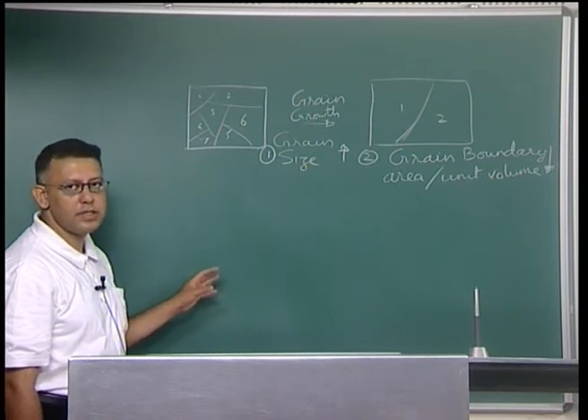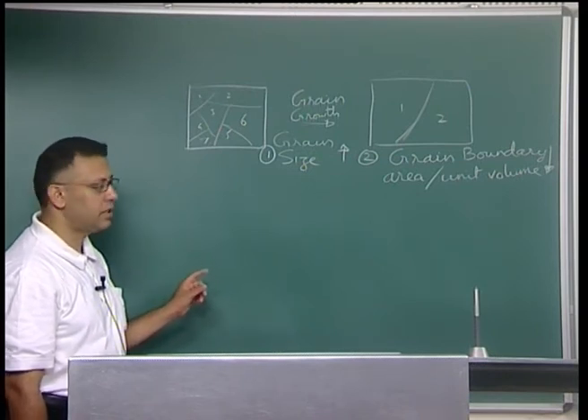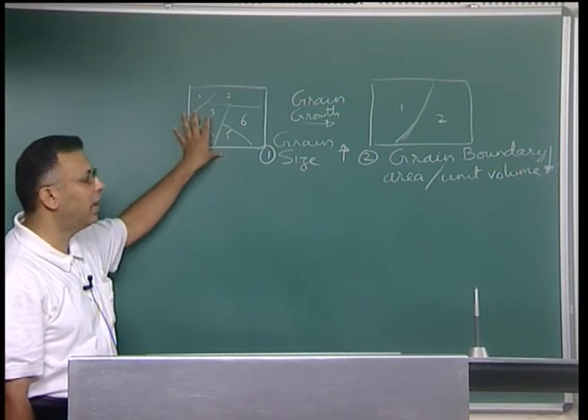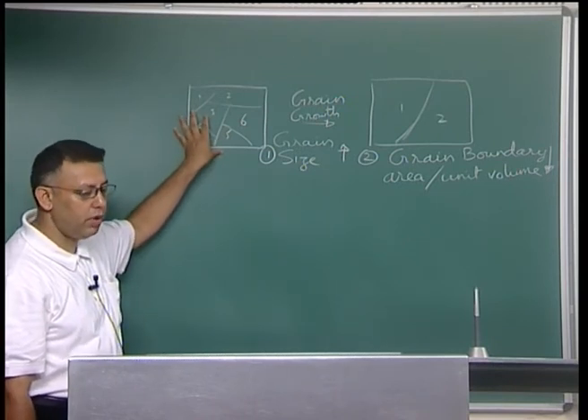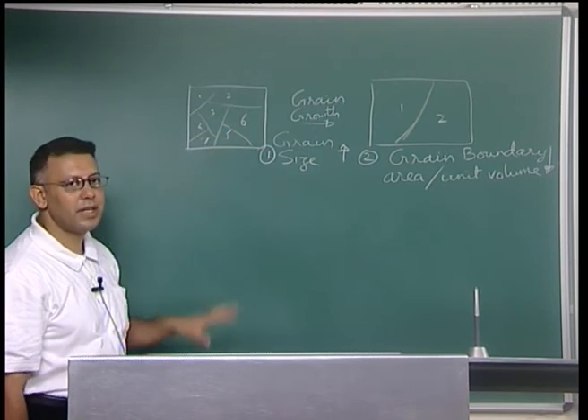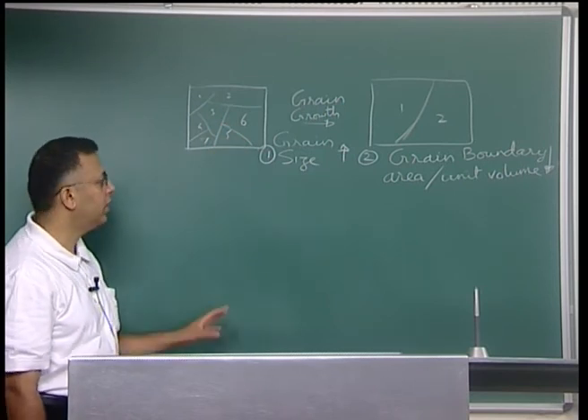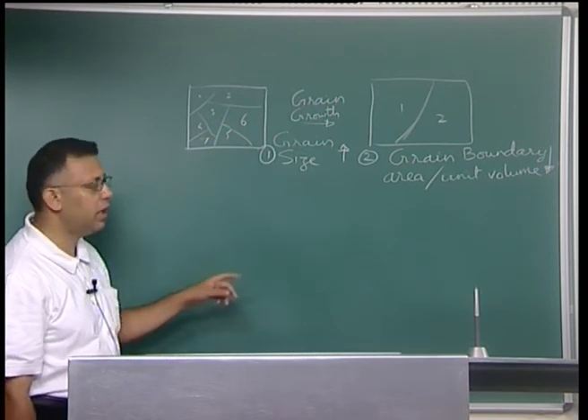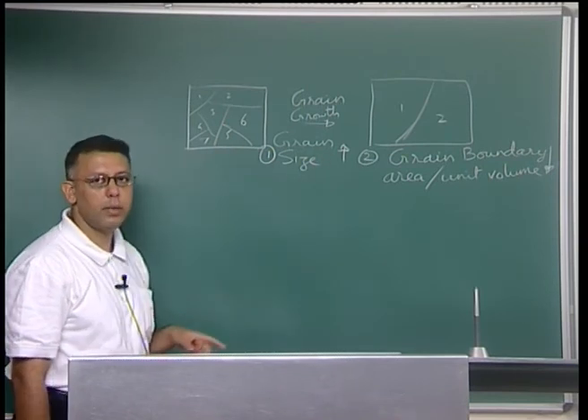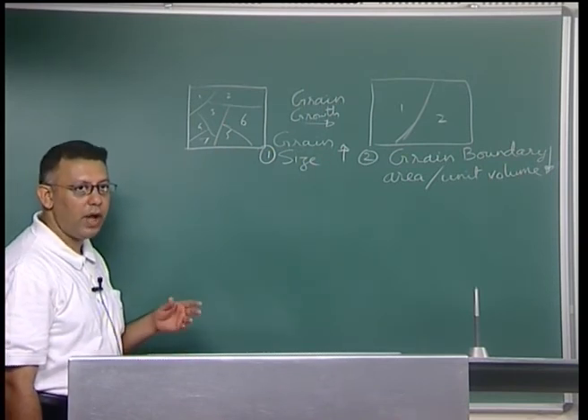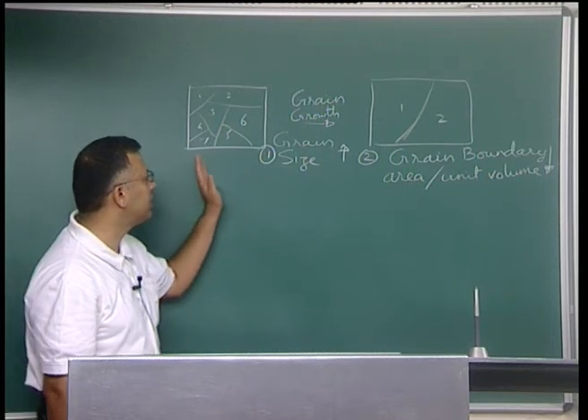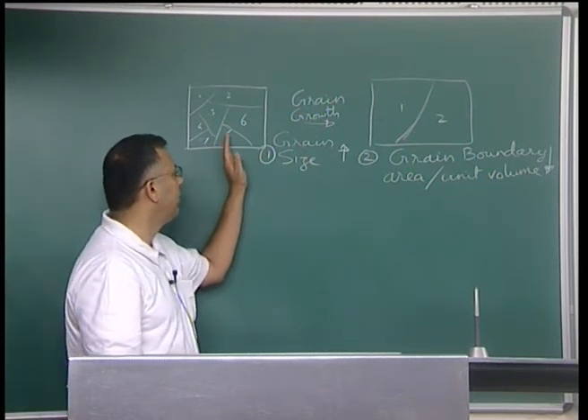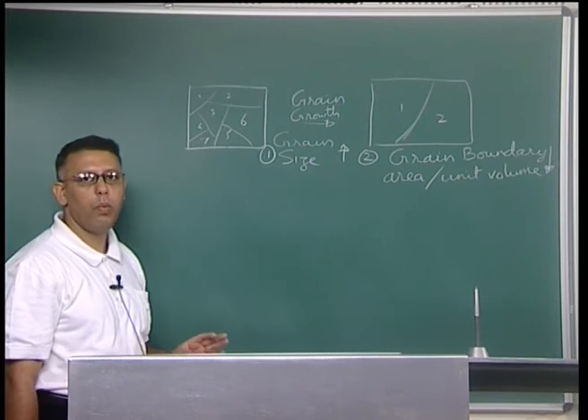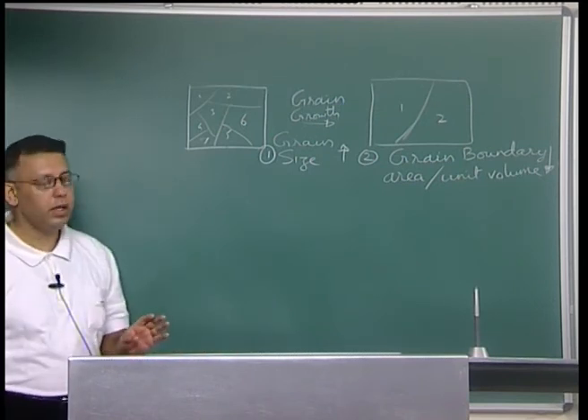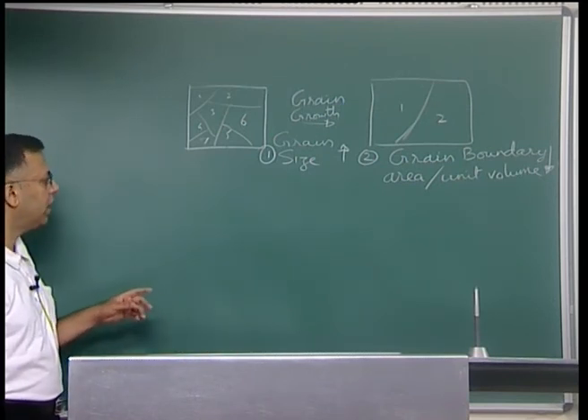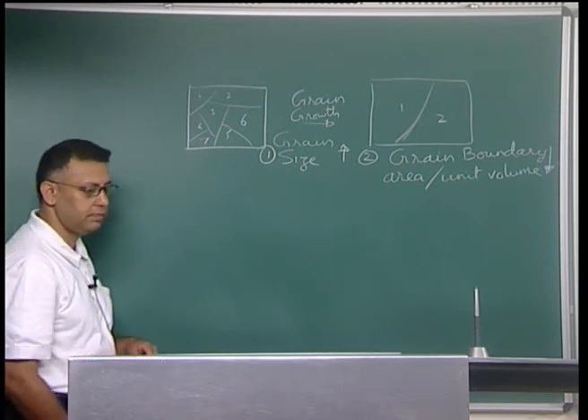Because of my increase in grain size, further my strength decreases as compared even to a recrystallized state, because the grain size goes into the Hall-Petch relationship for the determination of strength. That means my yield strength would decrease when I go from here to here. Even though the dislocation density does not change much when I go from a fine grain to a coarse grain during grain growth, my overall strength can drop because of the Hall-Petch effect.